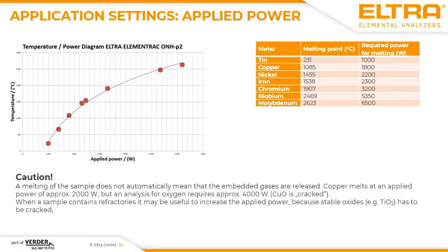But please be aware that you have to not only melt the sample, but also crack the bondings inside. This means copper, for example, will melt at 2000 watt, but the bonding of copper oxide inside the sample will only be cracked when you apply a higher power of about 3500 or 4000 watt at minimum. So this should be a rough orientation when you have an unknown sample, maybe an unknown slag, and you know that, for example, silicon oxide or titanium oxide is inside. Then you also have to apply a very high power to make sure that the sample is melting on the one hand, but on the other hand, that the bondings inside the substance are cracked.